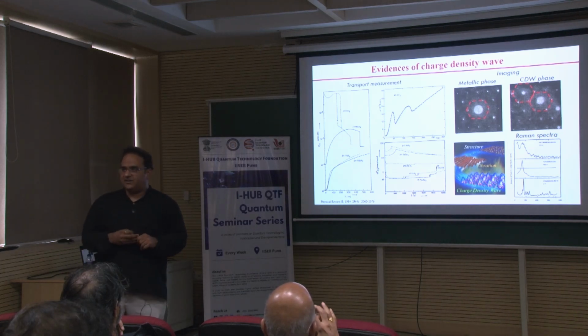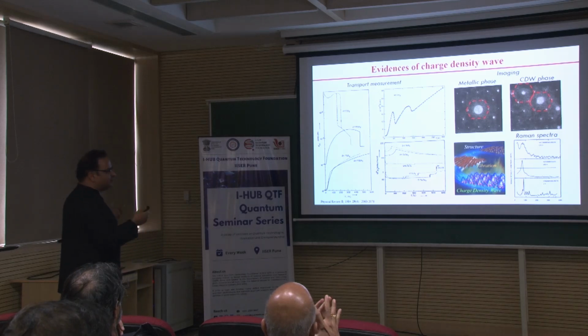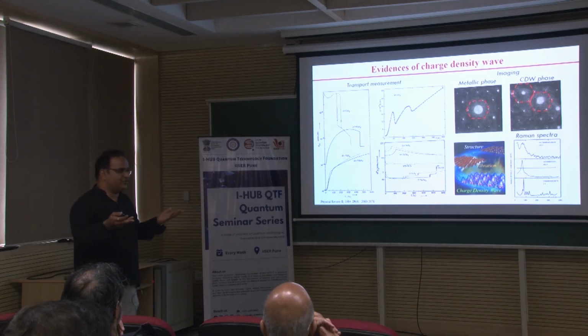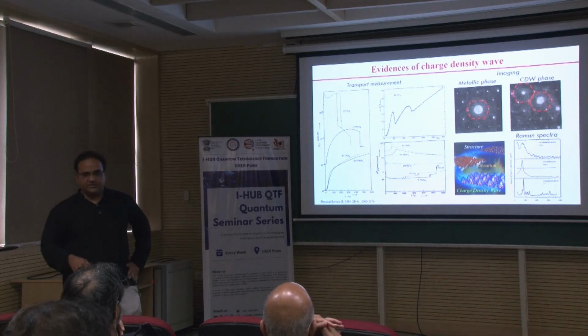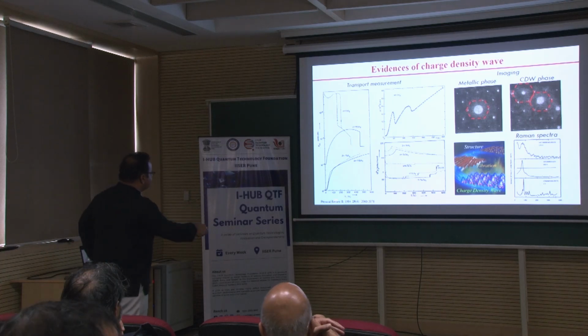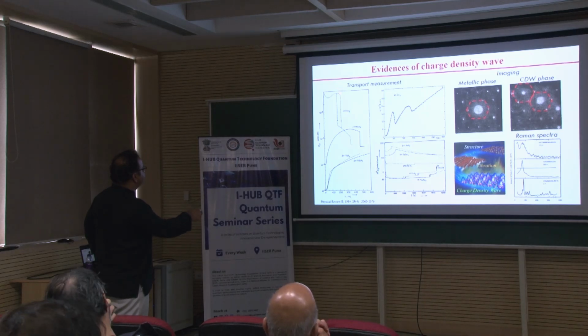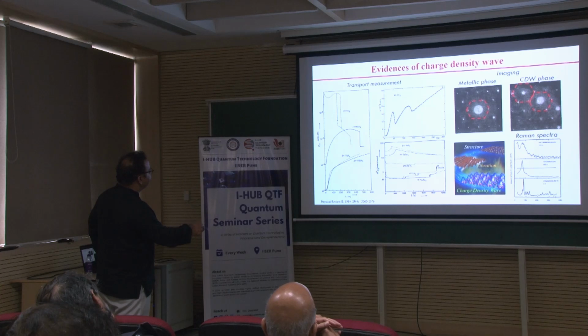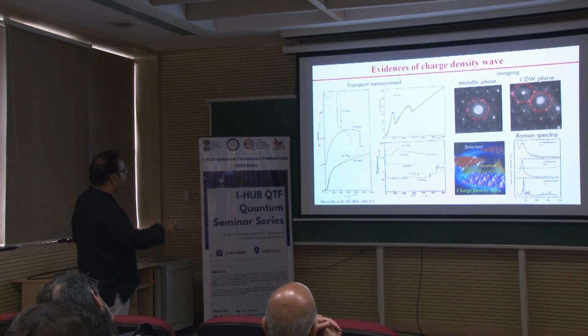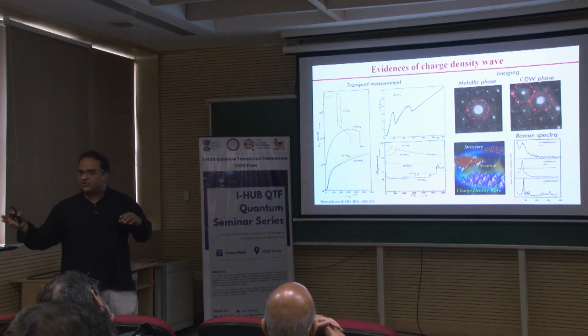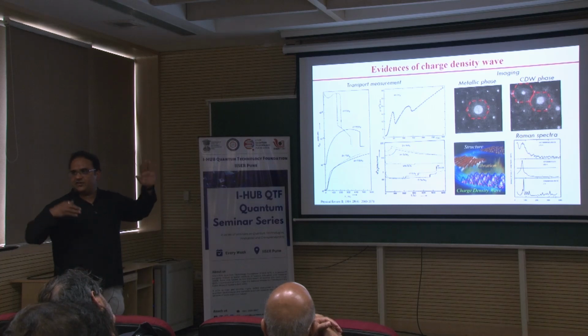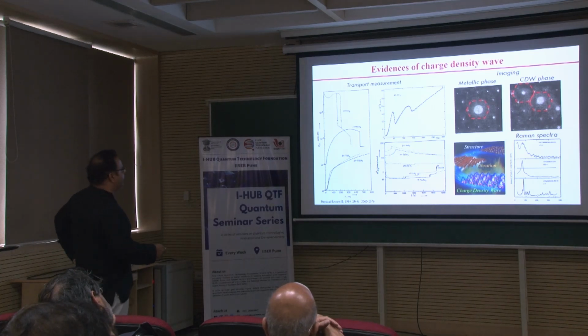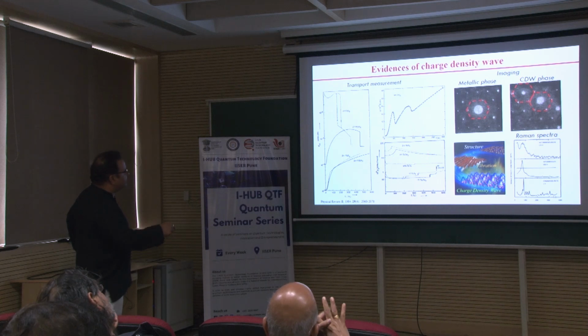Suppose you have a material, and how do you see there is a charge density wave? Because I am talking about electronic instabilities, how do you detect them? You do the transport measurement and you see that there is an anomaly or a deviation from the usual behavior. So, this is resistivity as a function of temperature. If you look here, this is 1T tantalum sulfide. You have a first-order phase transition-like behavior, but there is a charge density wave here. You have 1T tantalum selenide, there is a jump and then this is the behavior. So, these are actually the signature of the charge density wave. Now, there are other ways also to explain this. You have metal-insulator transitions, you have structural phase transitions, and all those are involved. But these are the materials which show the charge density wave.